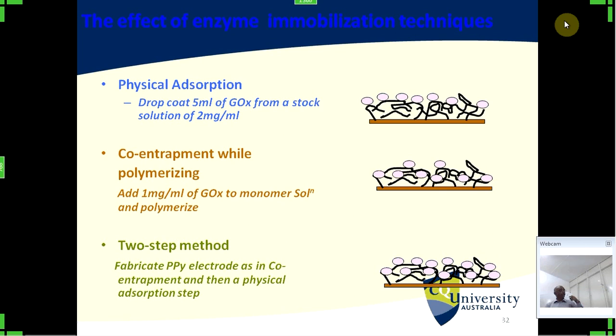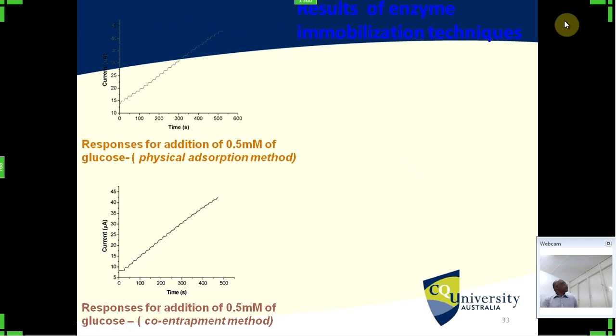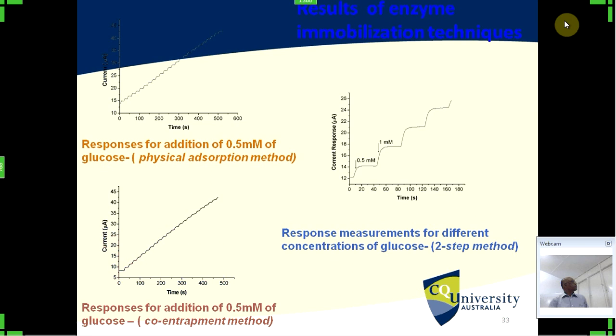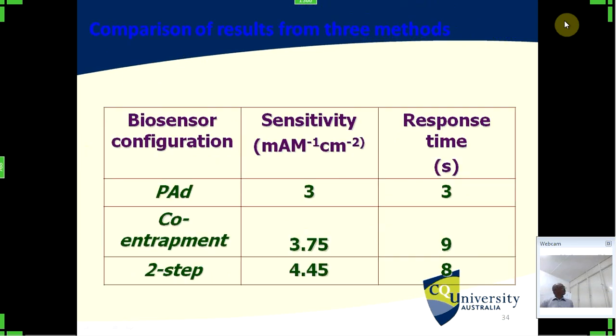In the two-step method, we did this one, and on top of that, we did so these are the results. And two-step method gave very high jump, smooth high jump, and becoming stable very soon. This is the sensitivity and the response time, the physical adsorption, co-entrapment, and the two-step method. But unfortunately here, inside the chain, so they take more time to react to the glucose.